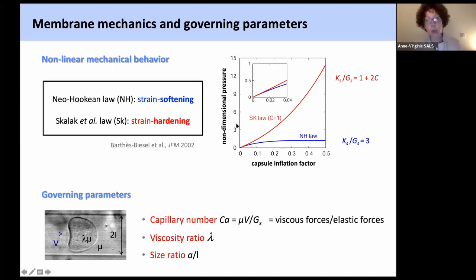Strain softening materials are defined by a tension that decreases the more you stretch the material: the easier it gets to stretch it. We have shown in the past, and I'll show you today, that this works really well for albumin capsules or for any protein, any material made of polymer. So any material that is designed by human beings and that has only one component, these laws work really well. But for biological tissues,